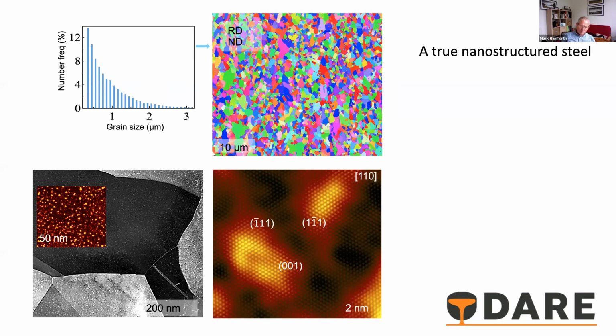But in fact, we found some very interesting properties. And we found that if you cold roll the steel, so it just needs a conventional hot rolling process, and then you take it through and give it a cold roll, and then flash anneal it, so a very short anneal, you can get recrystallization to a very fine grain size. So that's quantified on the top left there. So this is in microns.